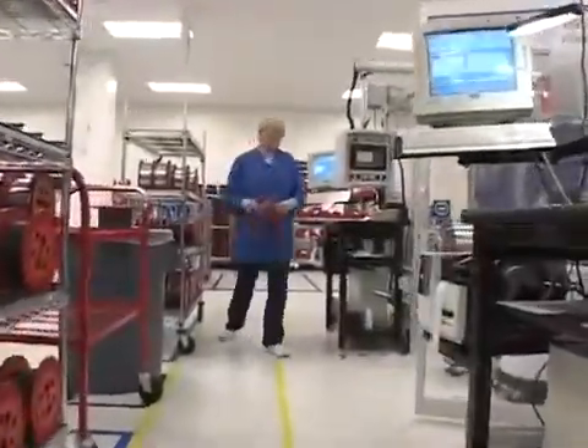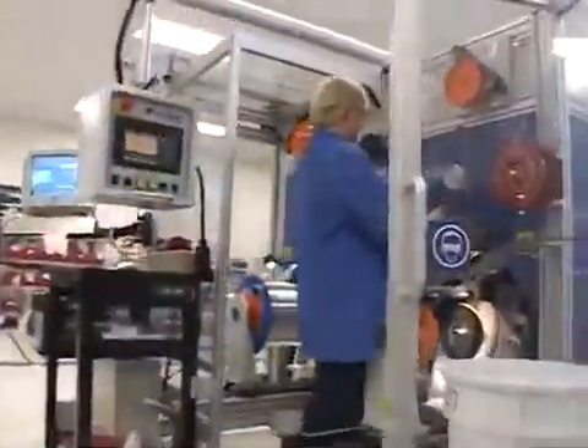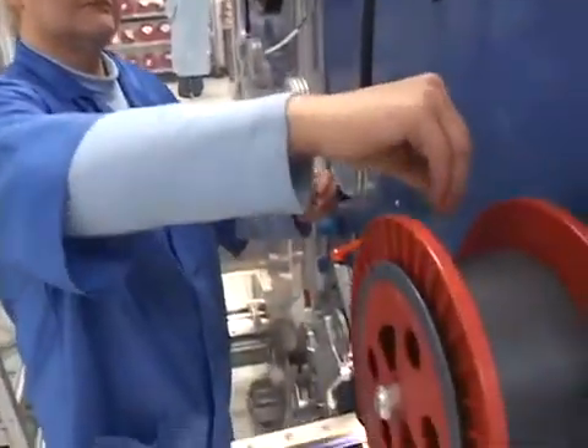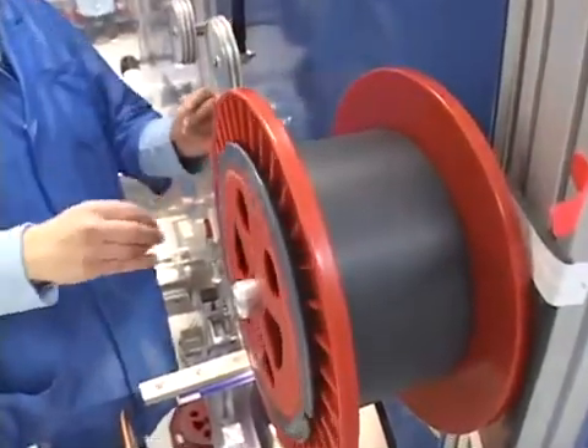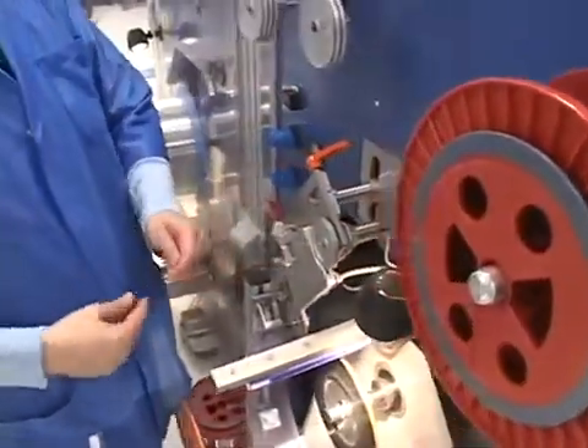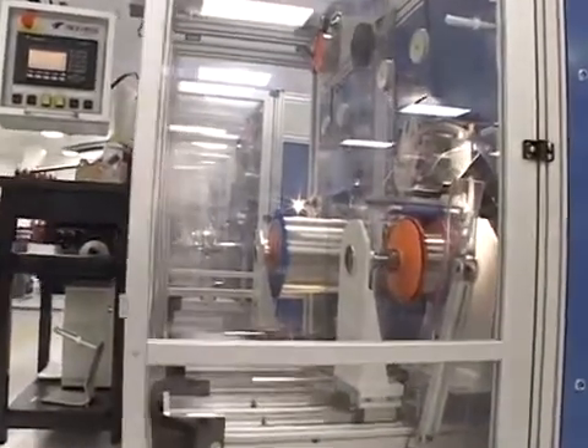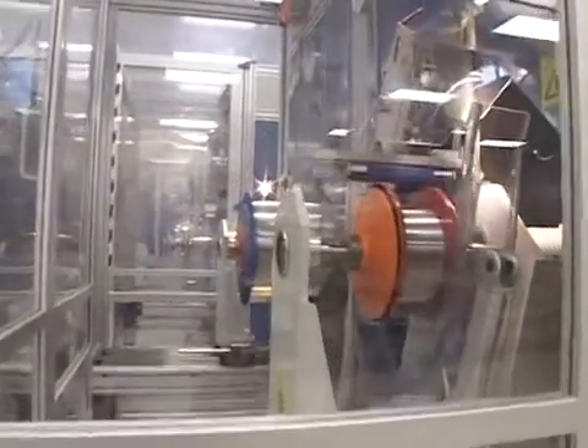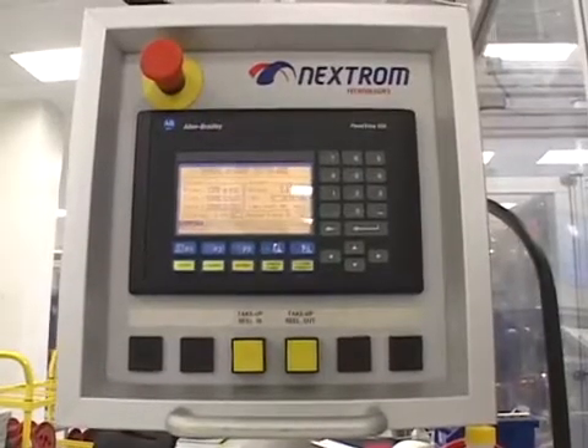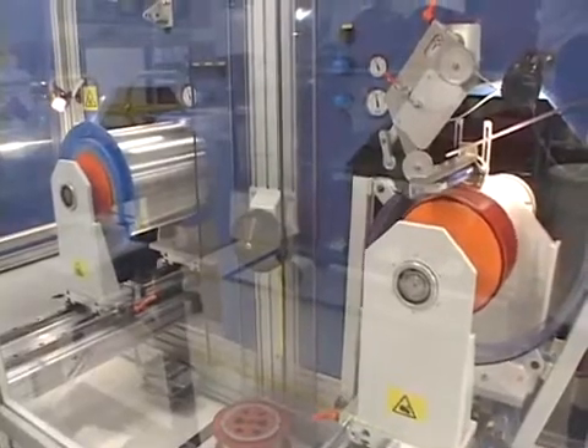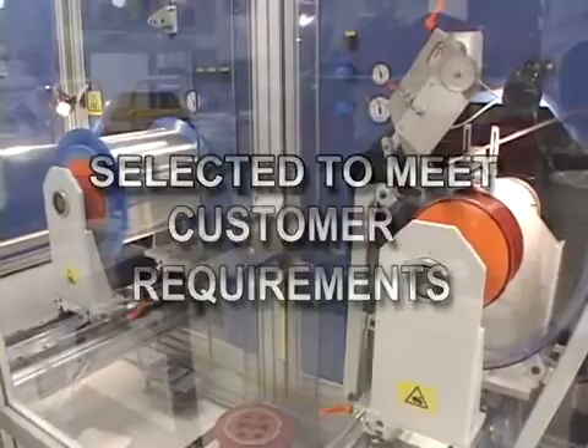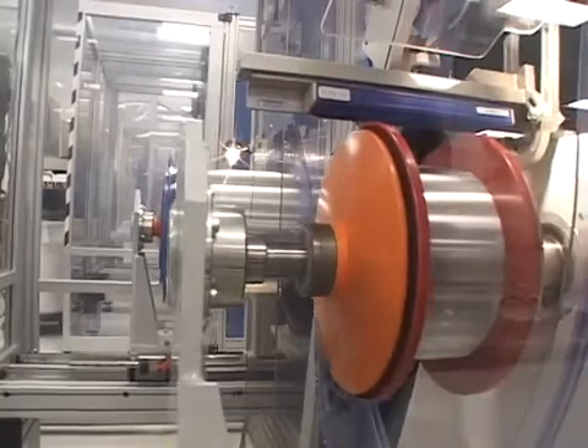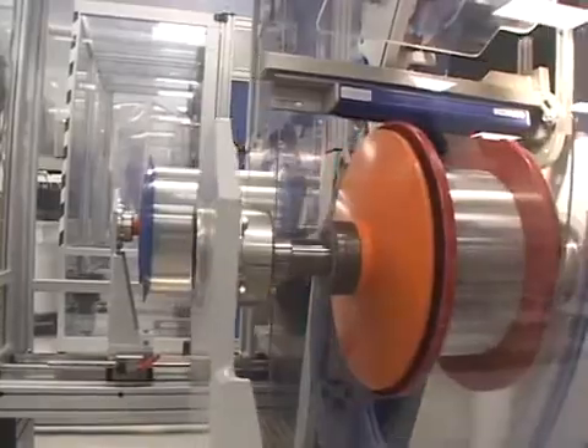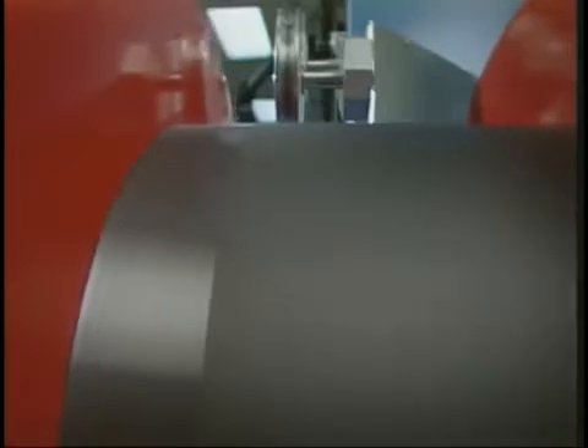After the preform draw, the fiber goes to test and measurement, where highly trained technicians subject each spool of fiber to a series of stringent mechanical, optical, and geometric tests. Throughout this highly automated testing process, measurement data is continuously added to online documentation so that the spools of fiber can be selected to meet specific customer requirements. The fiber must prove to have a tensile strength of at least 100,000 pounds per square inch before it's wound onto the spool using advanced technology that provides the highest wind quality.